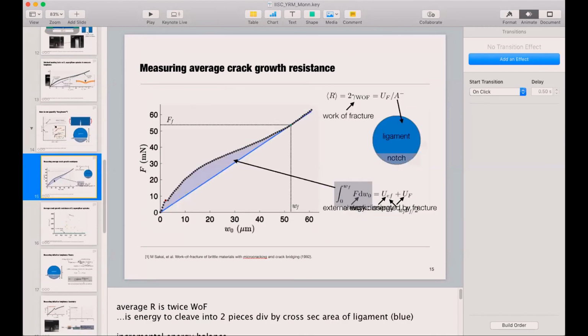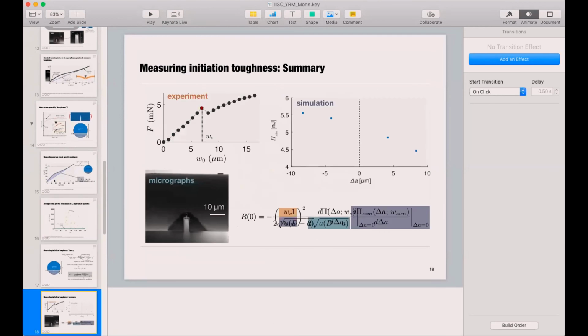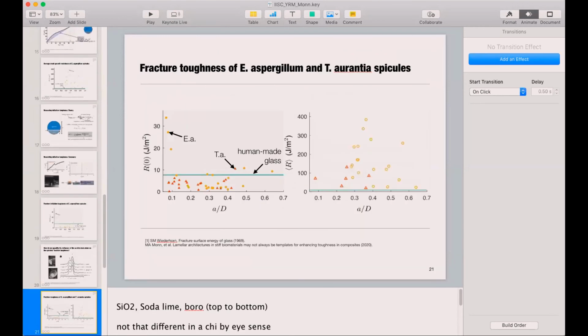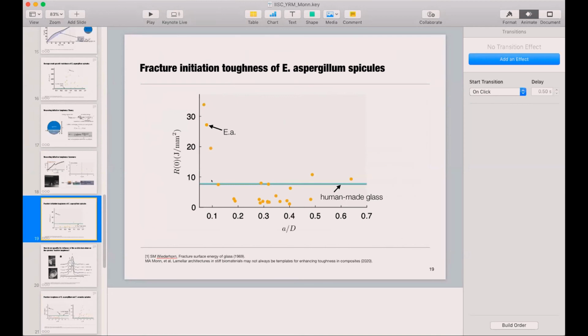But our first take at it is really this one: as you move towards the periphery of the spicules, the cylindrical layers get thinner and thinner and thinner. And so the effect of these type of mechanisms where you have daughter crack growth, crack arrest will become more and more significant for short cracks because they're going to be able to see more interfaces in front of the crack tip at the same distance. If that makes sense.